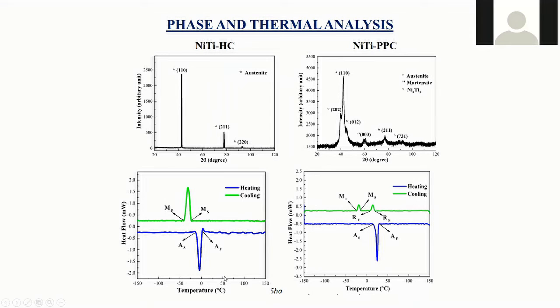In differential scanning calorimetry, you can see that in the case of the precipitated one, we have two very distinct peaks, where one is for the R phase transformation and the second is for the martensite transformation. Now, this is when we are not applying any stress to it. We are simply doing the temperature change, and this is what we are going to see, right?